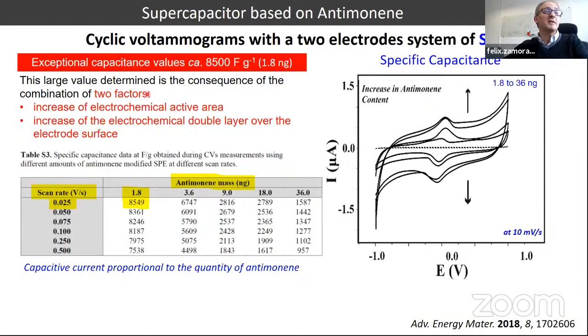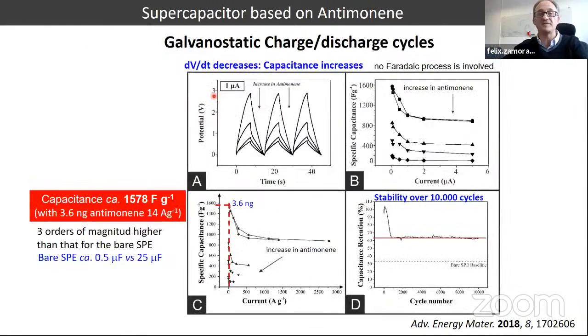Okay, so we end up with this exceptionally high value of capacitance determined by this experiment, probably because of two factors. As you locate antimony on top of the electrode, you increase the electrochemical active area of the electrode on the one hand, and on the other, you also increase the electrochemical double layer over the electrode surface. So probably we have this nice result because of these factors.